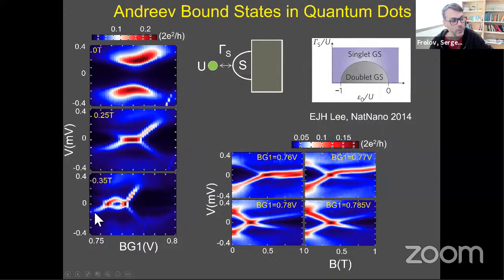And then when we keep going, we start seeing these kind of loop shapes, and the 0 bias peaks move around. So as a function of gate voltage, we see all these different pictures. For instance, look at 0.78. We see resonance at positive voltage, resonance at negative voltage meet and make a 0 bias peak for a very short range in magnetic field, and then they split further. So this is just, think of it as Zeeman splitting of spins. There are Andreev bound states at finite bias, and then they Zeeman split and cross at 0 bias, and they just keep going. That's the kind of a generic situation.